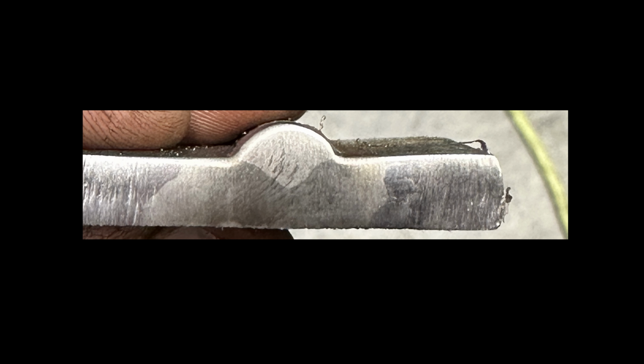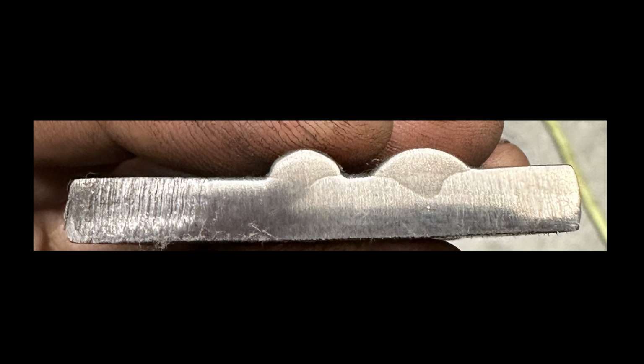Let's look at another test. Both of these were done with a short circuit process. The one on the left was with 140, 150 amp MIG welder settings, so pretty poor penetration. The one on the right, higher settings than the previous picture. Now we have a lot better fusion with the higher settings, as would be expected. Also, the plate was hot because I did the second pass right after the first. Now, spray arc, essentially the low end of spray, is at the high end of the performance you would expect with short circuit MIG.